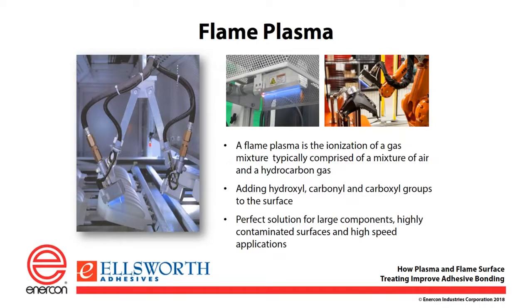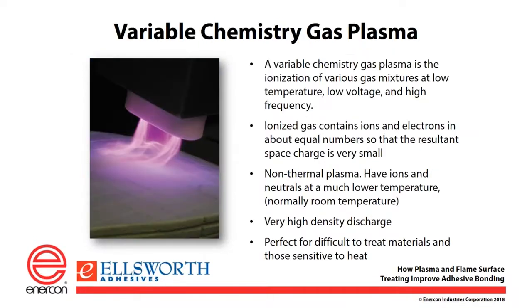Flame plasma, again, you're adding different functional groups to the surface, but in general, you're getting similar applications or you're getting similar results in increased surface energy onto the surface, but you have more flexibility in the size that you can cover. And when you have an odd-shaped application like the dashboard that you see on the right-hand side, which obviously has many different levels, it is easier to treat that with a flame because you do not have to be quite as precise with the distance that you are from the flame to get an increased amount of surface energy. And then we have some variable chemistry plasma.